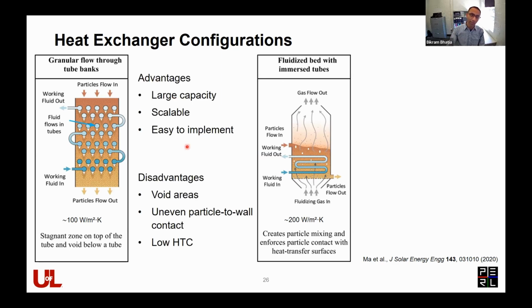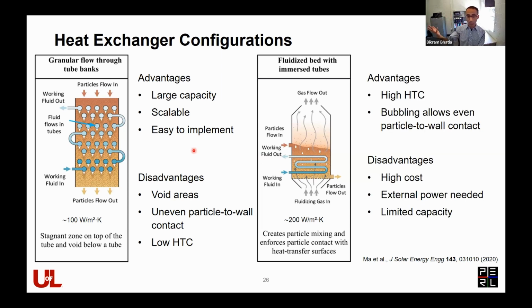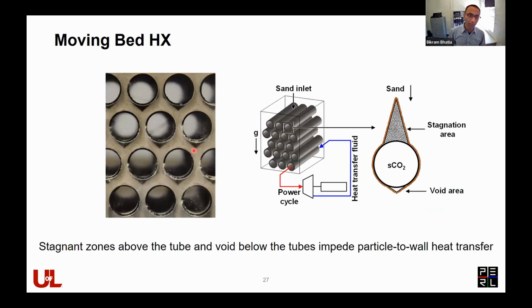So a tube bank heat exchanger is really easy to implement. It is perfectly compatible with a power tower application. You can have a scalable heat exchanger based on your application. The problem though is that the heat transfer coefficient from the solid particle into the tube wall is not very high, so the overall heat transfer coefficients are low. On the other side, you have the fluidized bed heat exchangers. They can give you a much higher heat transfer coefficient, but the problem is that they are complicated to integrate with the CSP system and can have a lot of parasitic losses associated with them. So those are the pros and cons of each. We've looked at both. I'll start off with the work that we did on tube banks.